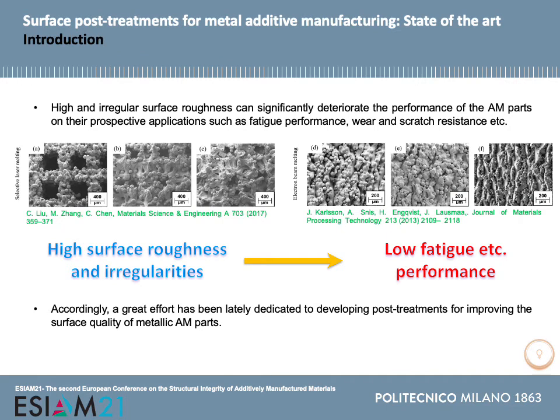Here as an example, you can see surface morphology of fabricated AM materials using different technologies of selective laser melting and electron beam melting, considering different process parameters. Irregular surfaces with poor surface quality with lots of unmelted and partially melted powders and spatters can be seen on both fabricated samples by different technologies.